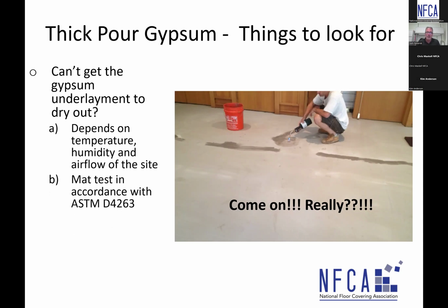To confirm dryness, an industry standard is ASTM D4263. And I'm not saying that this is a suitable test for concrete that's on ground to validate to put flooring down, but from an evaluation to see if a specific product is dry, it's suitable for that. So mat testing, basically throwing a piece of plastic down 24 by 24, letting it go 24 hours, making sure we don't have a dark spot underneath there. And that's only for mixed water. I'm not talking substrate moisture whatsoever. This is only mixed water that I'm referencing here.